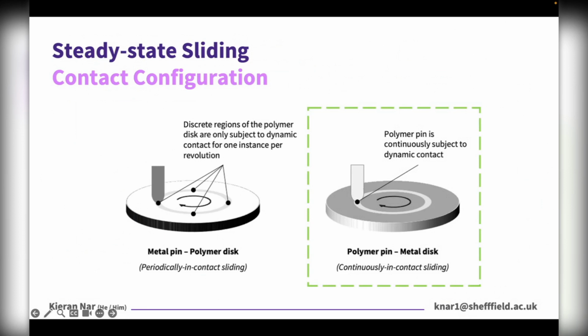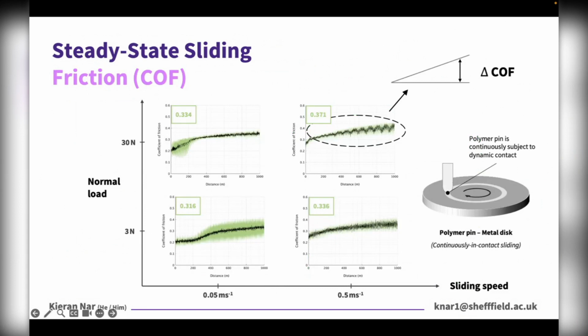If we look at the results recorded for polymer pin on metal disc sliding, we instantly see these steady increases in coefficient of friction. This was due to the buildup of frictional heat during testing, which led to thermal softening and subsequent enlargements in contact area.